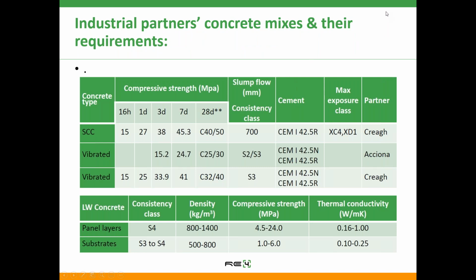So in terms of the concrete mixes from the industrial partners, you can see that there is the self-compacting concrete with 28 days strength complying with the C40-50. You've also got the cement type that is being used. So some, like the SCC and some others, were using rapid hardening, while others were using normal hardening cement. We've got a vibrated concrete, two strength grades, C25-30 and the C32-40. So where these original mixes came from are listed on the right-hand column of the table. Some of the mixes came from Creagh in Northern Ireland, and some came from Acciona in Spain.